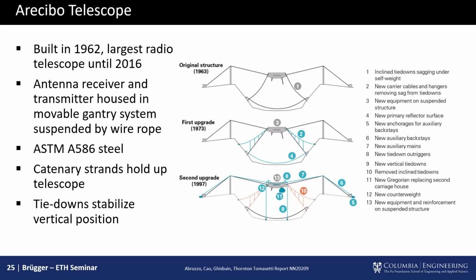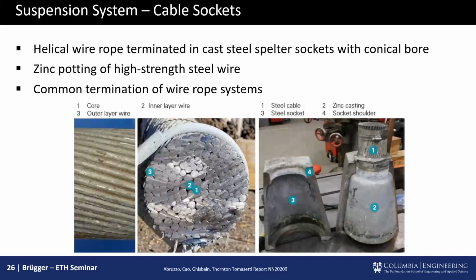So for the various radio measurements, they wanted to keep that stable. But of course, as a civil engineer, when I start seeing this thermal effects and somebody tying it down, this sends up warning lights. How was this tied down? Well, it was tied down with these typical wire ropes, as you would also find, for example, on cable cars. They're slightly different, but ultimately the same beast. And they're terminated in this case in these spelter sockets. And these sockets are literally just a steel wire, which is broomed out mechanically, manually by hand, and then filled with just elemental zinc. So you essentially have more or less these super high strength steel wires held together by bubble gum. And if you fan out those wires properly, then you essentially get a hydrostatic stress state in the zinc, which then makes it more or less quasi-incompressible and makes it hold its shape. So this is stable if done right.